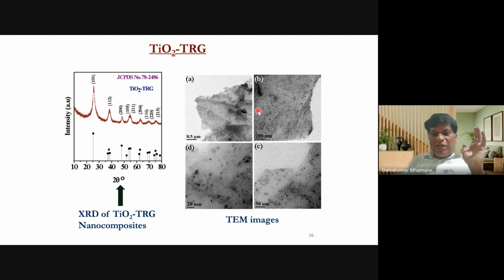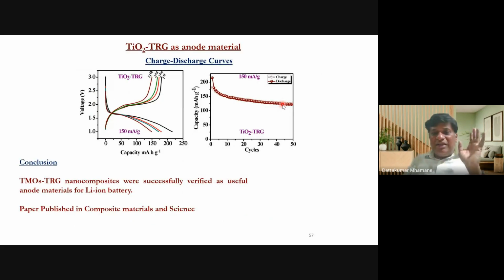TiO2 did not perform that well. There was some problem with the precursor, but the images are very good. All the TiO2 nanoparticles are covered on the graphene sheet. So this we did in only a single method we developed. This is a bit lower result. People showed more than 200 capacity, but in our case the capacity was less, maybe because of some impurity.